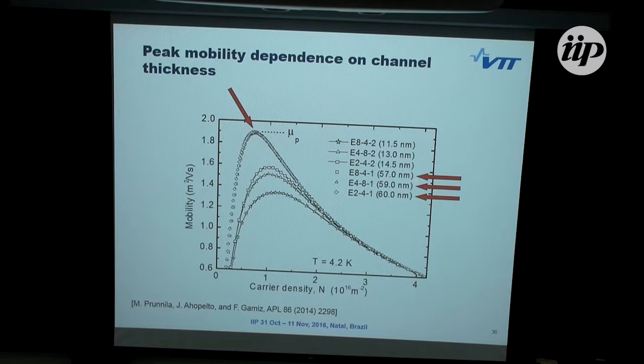When the channel thickness is around 60 nanometer or so, the peak mobility is about 20,000, which is rather good for silicon. I know that there's one report from Russia where they claimed 70,000 for silicon, but 20,000 is quite good. Our best is, I think, 28,000, which is not bad. But the point here is that all these have the same peak mobility.